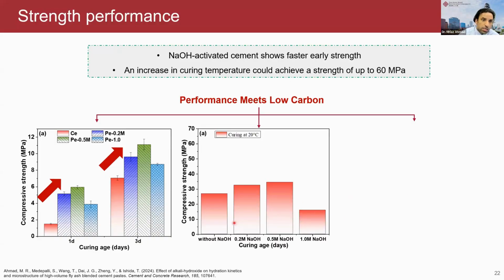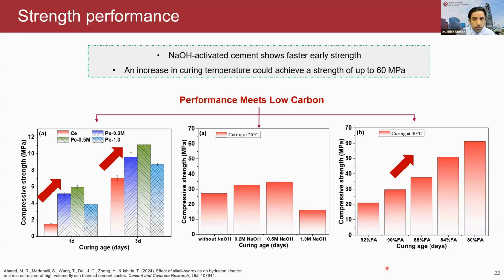And at 28 days, we still saw that the compressive strength was higher, around 35 megapascal. However, the significant increase we observe is at 40 degrees centigrade. So temperature curing, like I mentioned before, is extremely important if we want to improve the properties of this ultra low clinker cement, because it can boost the further reaction.